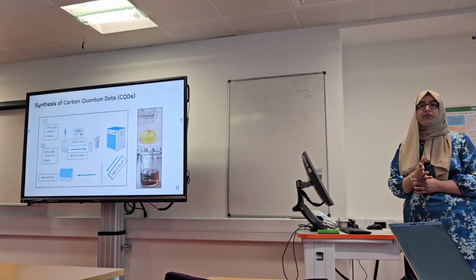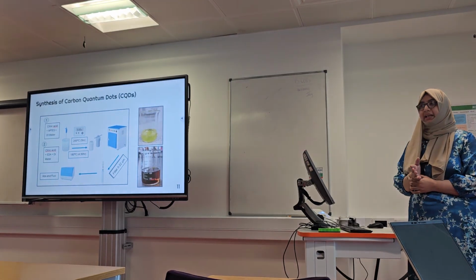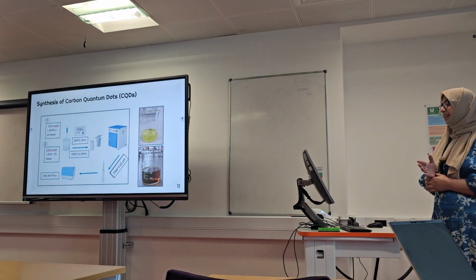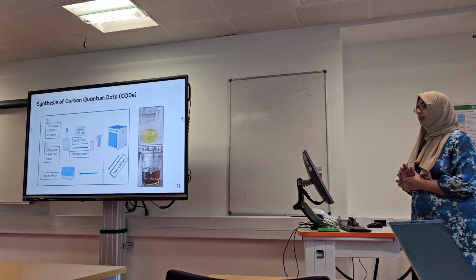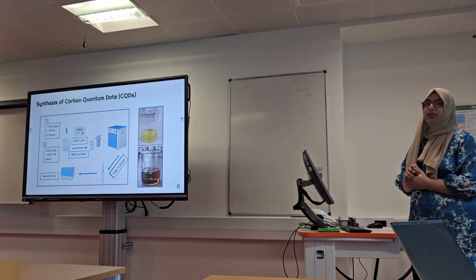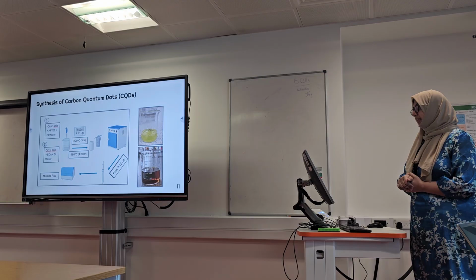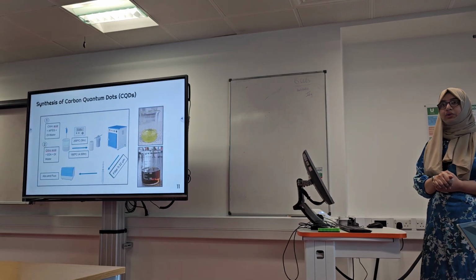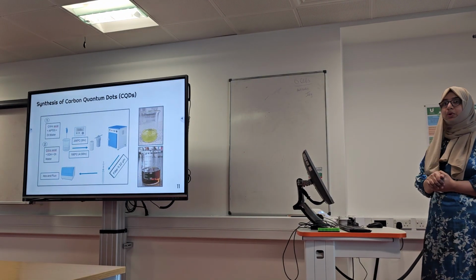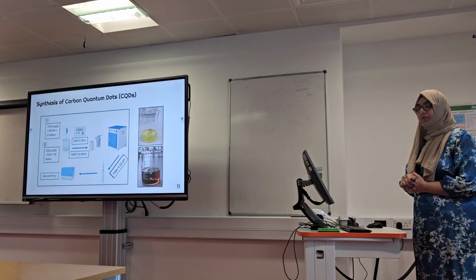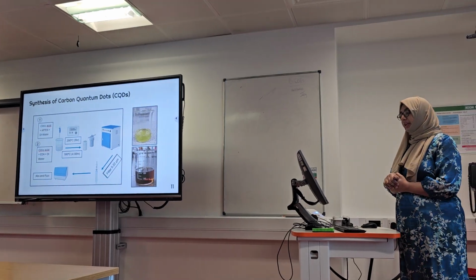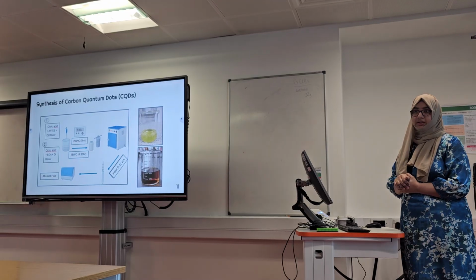I used 0.5 gram of citric acid and 10 ml of APTES, and then I put it in a hydrothermal reactor for 5 hours at 200 degrees centigrade. Then after that I filtered the solution using 0.2 micrometer filter paper, and then I checked the absorbance and fluorescence of the solution.